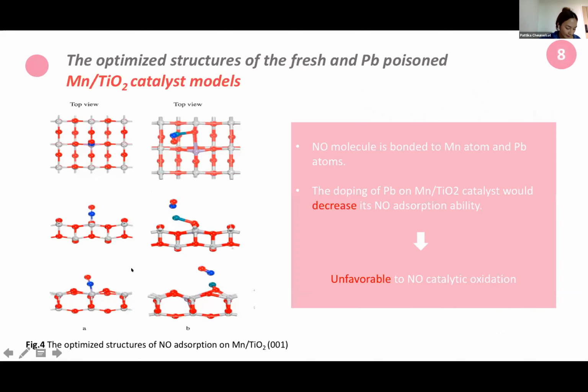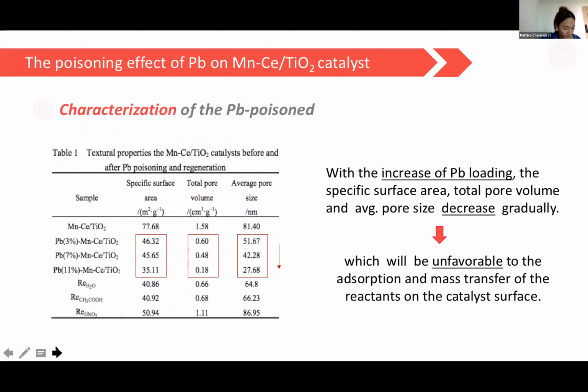reaction. The figure shows the optimized structure of NO adsorption on manganese titanium. The NO molecule is bound to a manganese atom and a lead atom. The doping of lead on manganese titanium catalyst would decrease its NO adsorption ability, unfavorable to NO catalytic oxidation. This slide shows the characterization of the Pb poison.